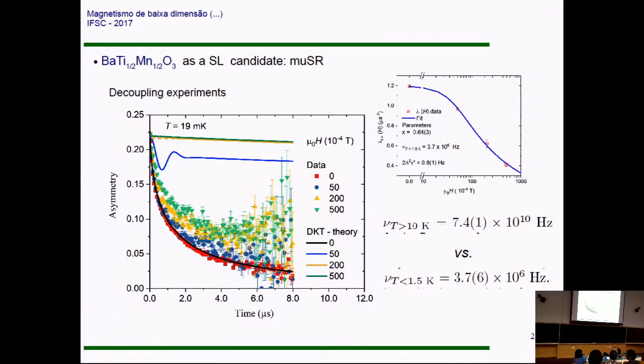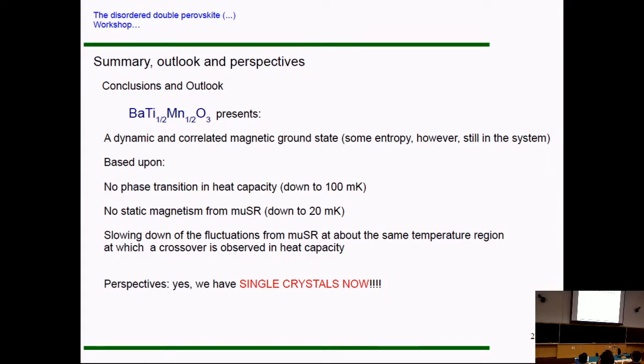So we have, say, a full order of magnitude decrease in the speed of the fluctuation. And this is usually interpreted as a sign of formation of entangled states that you should have in a spin liquid state. So just to finish the talk, what we just presented is that certainly this compound presents a dynamic and correlated magnetic ground state. Although when I say ground state, some entropy is still in the system, clearly.